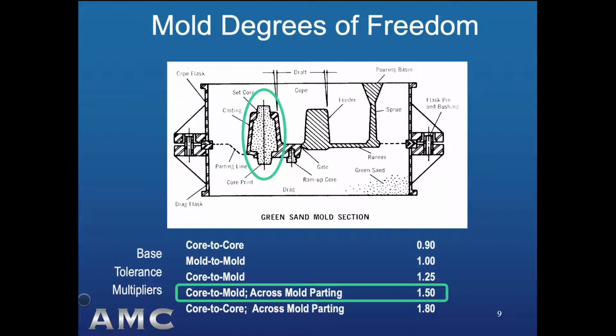Well, here we see a typical situation in a horizontally parted sand mold. Encircled is a tall core that is set in the bottom half of the mold. It has 2 degrees of freedom in the green horizontal box. It has a core to mold degree of freedom as that core sits in the bottom half of the mold, and it has a degree of freedom across the mold parting line as it goes across that parting line and connects with the top half of the mold.